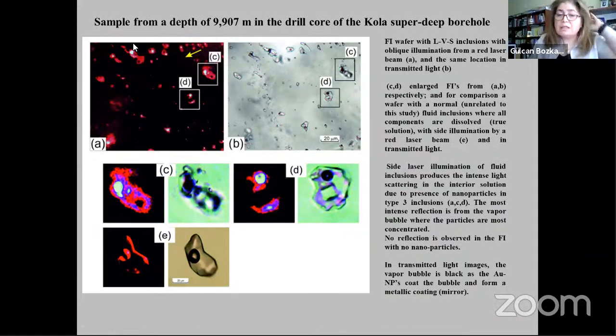In these fluid inclusions from the Kola borehole, the gold particles are true nanoparticles, much smaller, and are dispersed throughout the fluid inclusions. The inclusions are illuminated by shining a red laser at an angle and observing the reflected light. In inclusions without nanoparticles, there is no reflection from the solution. The only reflection comes at the interface between the quartz and the fluid vapor bubble. In the other images, we see bright red reflection from the fluid and intense white reflection from the vapor bubble, where there is a higher accumulation of particles, like throughout the fluid.